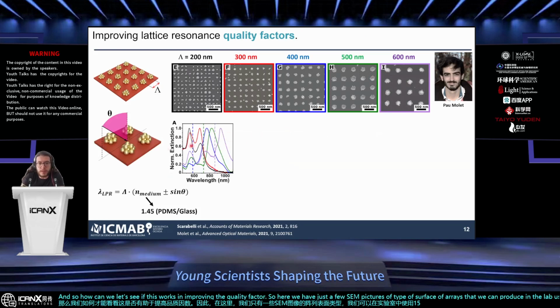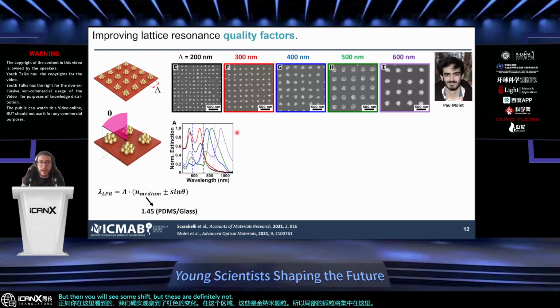And as you can see here, we do observe a shift to the red. In this area, these are gold nanoparticles, so the localized plasmon would be centered around here, but then you will see some shift, but these are definitely not sharp. And the dotted line that you see here is where the theory tells me that the lattice resonances should be. So you easily realize that the major peaks that you observe here are not the lattice resonances, but are still localized. This is because you have to keep in mind that these are clusters, so there will be near field coupling in here.